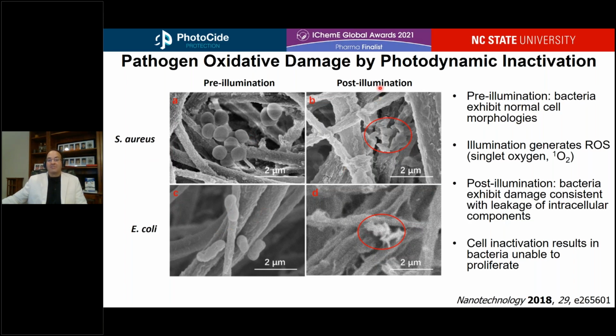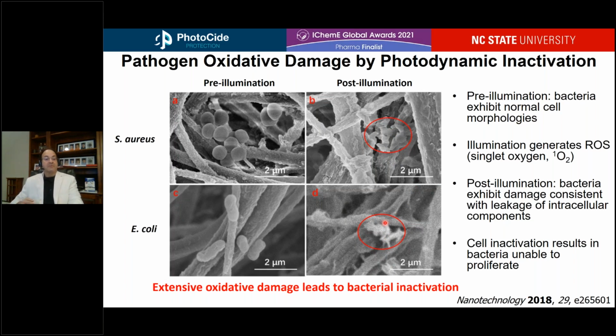But after the addition of visible light, you can see that the generation of reactive oxygen species, such as singlet oxygen, causes wholesale oxidative damage, extensive oxidative damage, leading to the inactivation of the bacteria. They're unable to proliferate when they are in this damaged state. If they're unable to proliferate, they're unable to be transmitted to new hosts and cause subsequent disease.